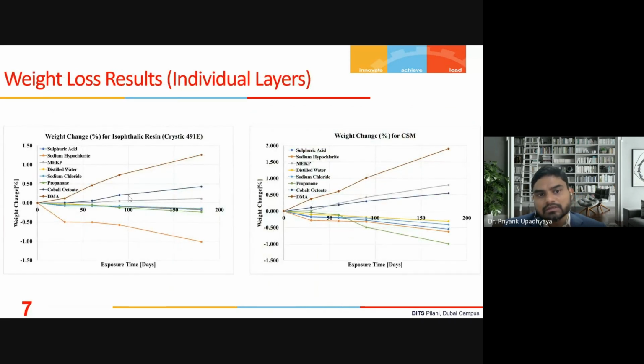Now coming to the results, this is the weight loss data that we have got for individual layers. So we have one isophthalic resin layer there. For this layer, you can notice that the significant weight loss is happening mostly because of sodium hypochlorite. And another thing that I wanted to notice is that all the chemicals that are being used as manufacturing process chemicals, all of them are not reducing the weight, but they are increasing the weight of the samples. Similarly, if you notice in terms of the weight loss for the chopped strand mat, you can see that the weight reduction is happening for all the chemicals except for MEKP, DMA, and the cobalt octave.